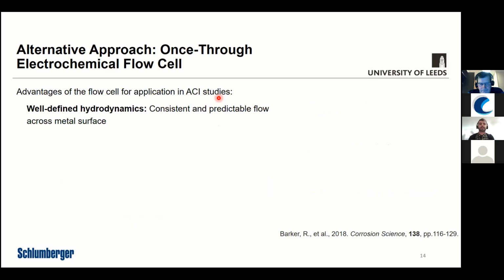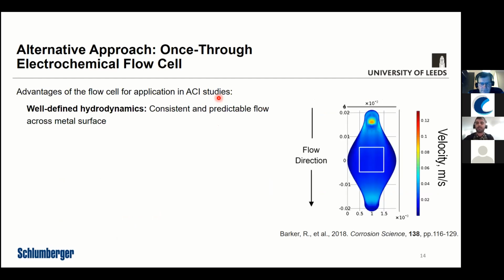So the advantages, as I've said, are that we've got well-defined hydrodynamics. That's useful. At the moment, we're limited to doing laminar flow experiments. It's a very low flow rate. But the key thing is that we get a consistent flow pattern across the surface, so we aren't introducing anything as a result of the experiment that could potentially influence the corrosion we would see, through some sort of hydrodynamic influence or the transport of any corrosive species to the carbon steel surface.